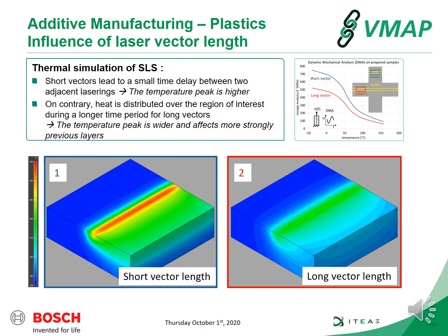The simulations in DigimatAM considering the laser path can also help to explain the difference in mechanical behavior between different vector lengths. Referring to the cruciform specimen already considered, you can see that the vector length in sample 1, which is the shorter one, presents a higher temperature peak compared to sample 2 with a longer vector length. The higher temperature peak will result in a better melting behavior of the powder and thus a better consolidation of the material. Hence, higher mechanical properties result.